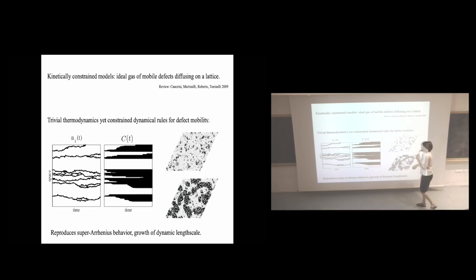So I'm showing here a simple kinetically constrained model in 1D. Here you have space, so this is x, and then time, so it's a space-time map. And the black points correspond to the positions of the defects which carry the mobility. And they have some dynamics, which means that they cannot just diffuse freely in space. There are some rules for them to diffuse. You see that the dynamics is constrained.